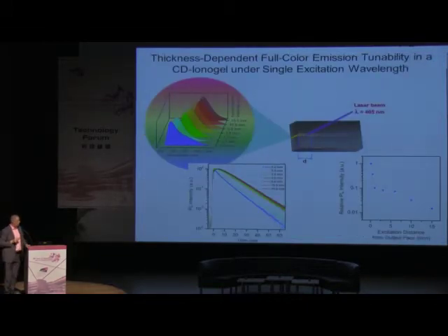And then what we found out was that if we take a block of such ionogel and we excite it at different distances to the edge, so we collect light always at the edge here, but we can excite it close to the edge or at longer and longer distances, we can actually change the emission of these ionogels, starting from the blue, if we excite it at the edge, going all the way through all other colors to the deep red color. And emission stays quite strong if we keep exciting at short distances, and then it decreases gradually if we go far from the edge.